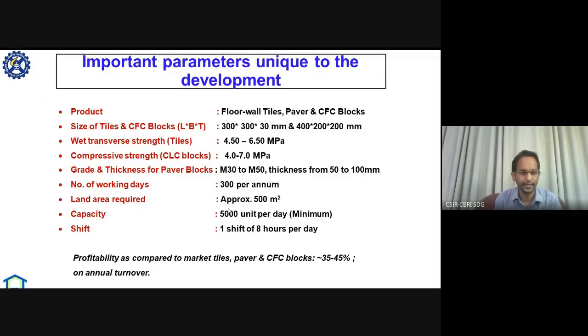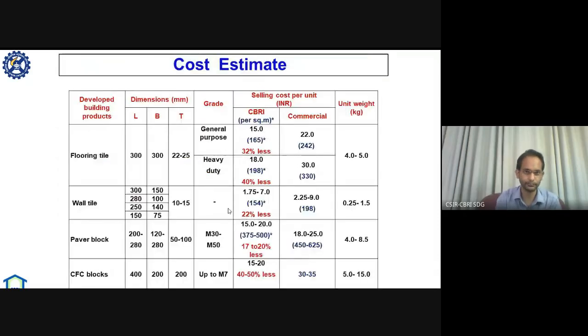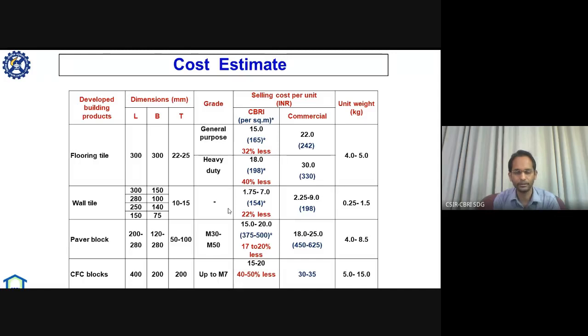After we did the cost economics analysis, we saw that the profitability compared to commercial tiles, paver blocks, and CFC blocks was approximately 35 to 45% on annual turnover. Here you can see briefly what we have done. You just see the selling cost. Here CBRI's tiles, flooring tiles, wall tiles, paver blocks, CFC blocks, etc. The cost is given per unit as well as per square meter, and the same is given for the same dimensions for commercial tiles. So you can see that for the CFC block, the overall cost was reduced by 45 to 50%.